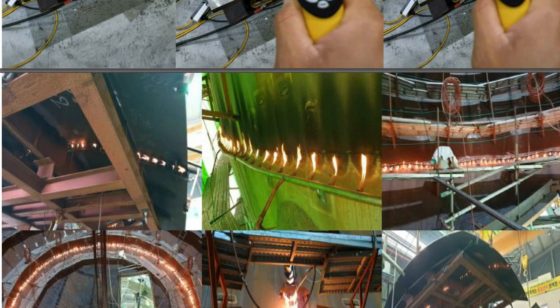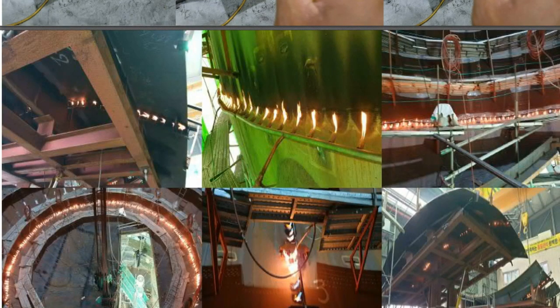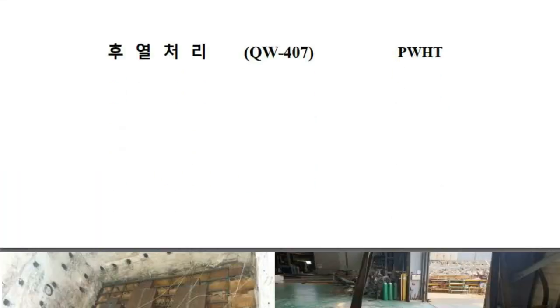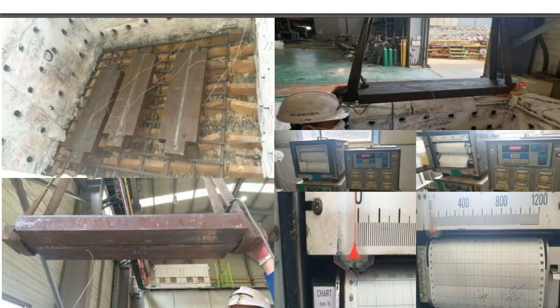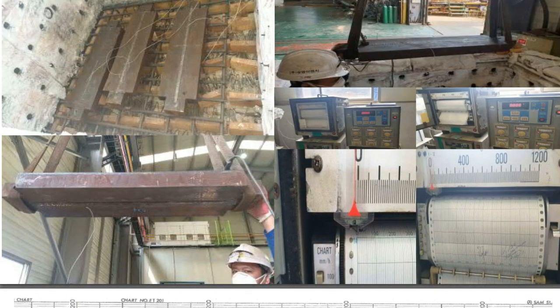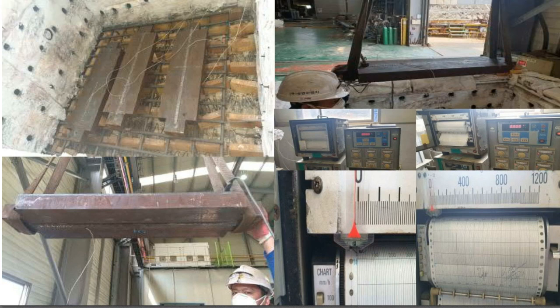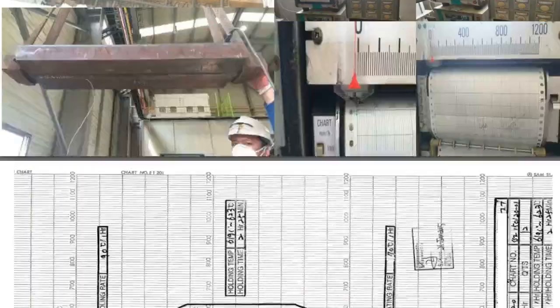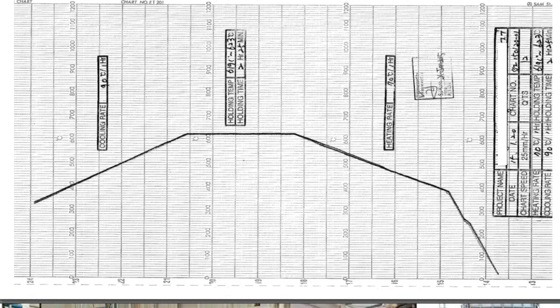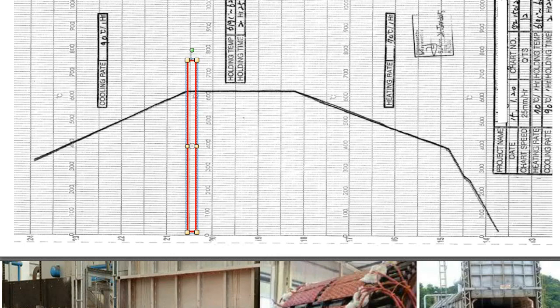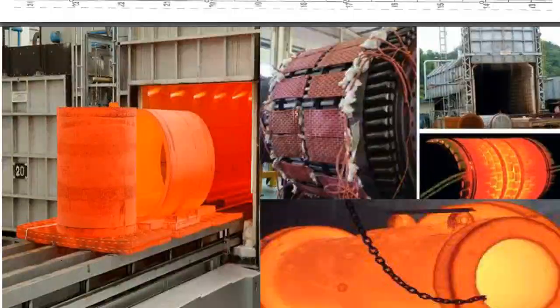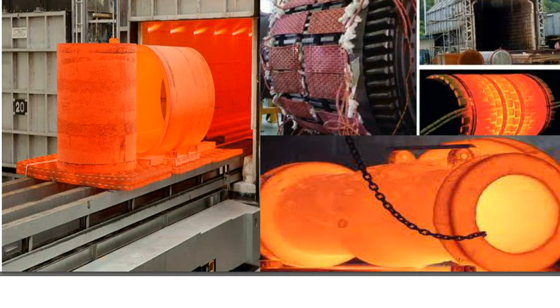And then after preheating, you do the actual welding, and then depending on the thickness or surface, you do PWHT. Here are some pictures of the PWHT. In the furnace, you put the weld coupon inside, install the thermocouples, and then do the PWHT with a PWHT temperature recorder and chart recorder, like here. This is the temperature range, about 600 something, and this is the holding time. You can see the kinds of heat treatment.